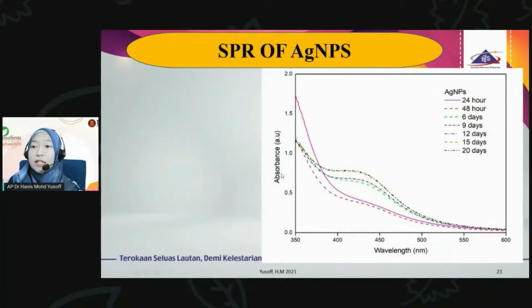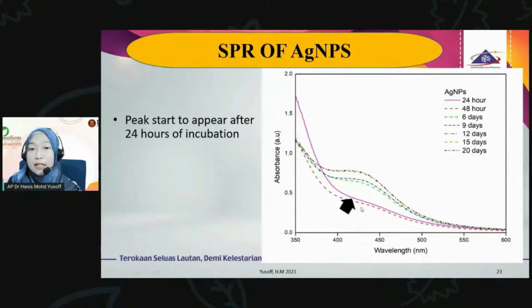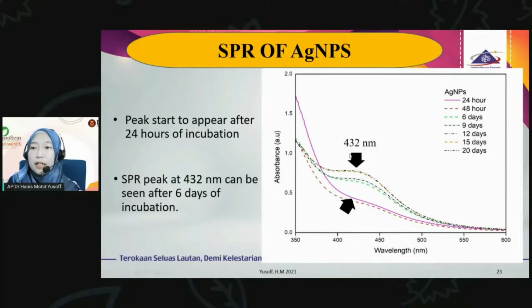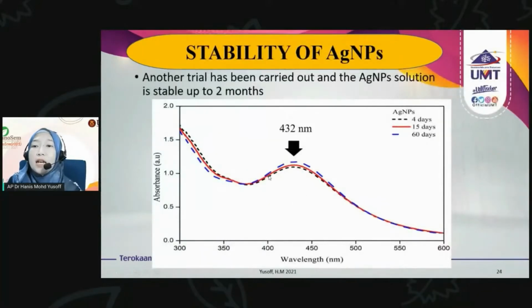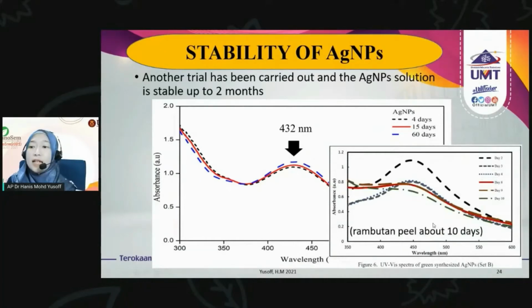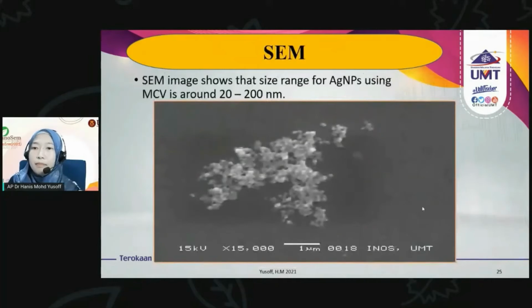In our study, by using this MCV, after 24 hours a peak starts to show. Then after about 6 days, the peak can be seen clearly at 432 nanometer. We also see the stability is up to 2 months. We have tried with rambutan peel previously, and the stability is only about 10 days. However, due to the limitation of our SEM instrument, we cannot obtain a very good image. So I'm very eager to collaborate and get nicer images of our samples. This is the best image that we can get at 15,000 times magnification, and roughly we estimated about 20 to 200 nanometer size range.